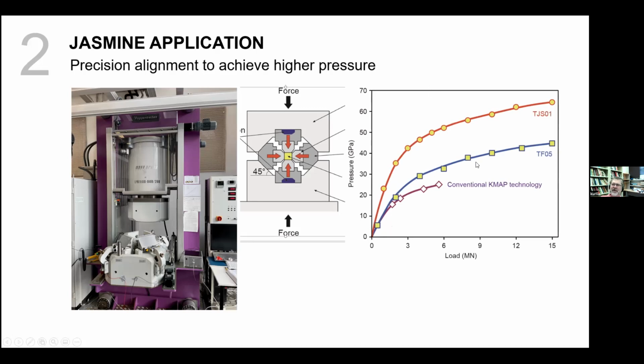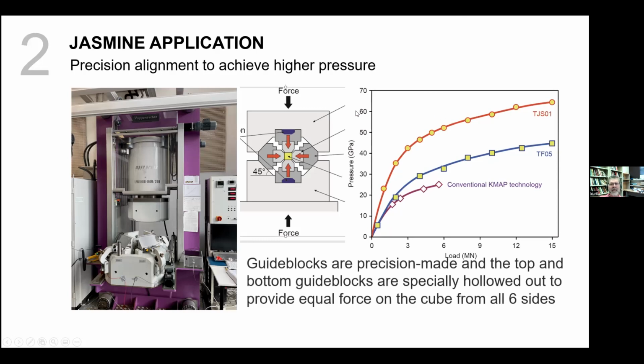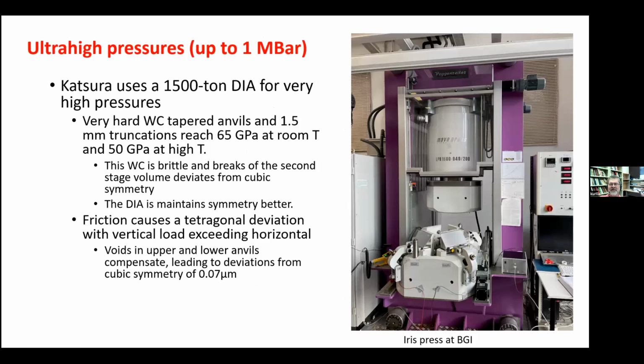So here's some of his pressure calibrations, and this is the normal multi-anvil. This is just with harder carbide and no other particular modifications. And then this is with tapered anvils. It's getting up to 60 GPa. We talk about a megabar. Sinter diamond has been taken over a megabar in Japan at Spring 8, and you could also do that here. Although, it's expensive, so hopefully there's a way to do it without breaking a lot of sinter diamond in the future.